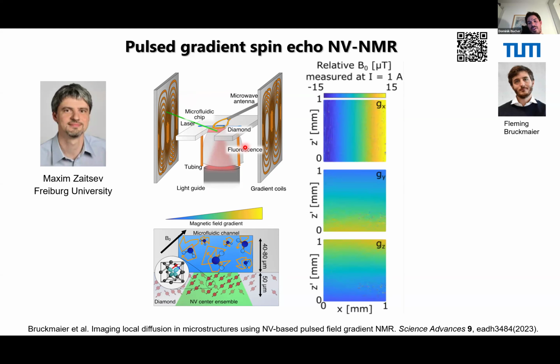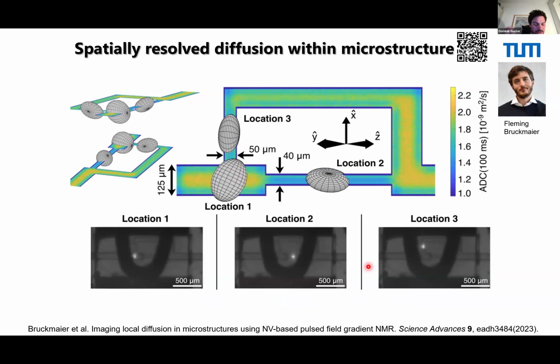And the good thing is with the NV center, of course, we can directly image and visualize the local magnetic field. And you see here the gradients which are induced by these coils can be in X, Y, and Z direction. And now I don't want to talk too much about the pulse sequence. So we exactly do this gradient spin echo. So we apply this spin echo with these pulsed gradients. And with this, we can calculate back the diffusion coefficient.